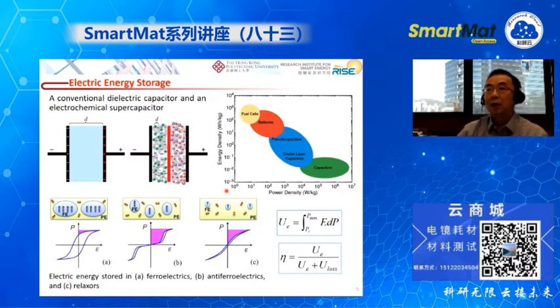So now in the next few slides, we'll talk about the first application for the ferroelectric material to be used for electrical energy storage. And the device we use is mainly the parallel plate capacitor. In comparison with the electrochemical supercapacitor, you can see for the parallel plate capacitor, all the charge are actually being stored at the interface between the electrode and the dielectric material. While for the electrochemical supercapacitor, those charges can be stored at the surface of the active electrode material. So since the electrochemical supercapacitor has a much larger surface area than the interface between the electrode and dielectric in the parallel plate capacitor, the electrochemical supercapacitor has a larger capacity or a higher energy density.